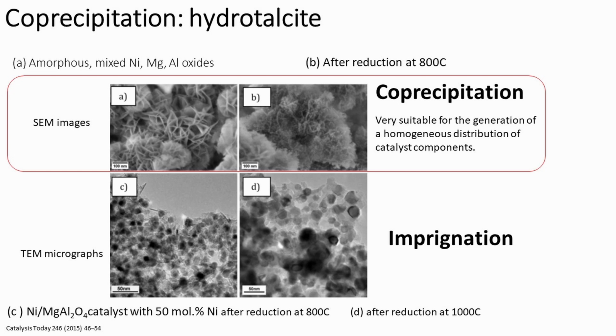A drawback of the co-precipitation process is generation of a large quantity of salt solution, and the fact that after precipitation the product has to be separated, which is mostly done by filtration. Co-precipitated powders can be shaped, but after shaping, a calcination has to be applied to achieve mechanical strength. The materials have to be heated up to 700 or higher.